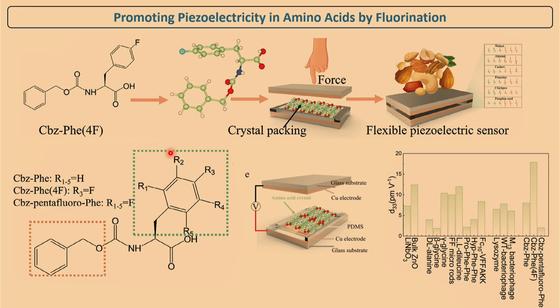And when they have done it, they have looked at the crystal structure, I am not showing all the details, and you can actually put that very nicely over there, and then you can tap force. And if you tap force, you can actually generate a piezoelectric response. And interestingly, you would appreciate that this particular molecule, where you have only one fluorine, has a very nice dipole in one direction, right? But if you have fluorine all throughout, then the vectors of the electronegativity will cancel out to some extent. That's obvious.